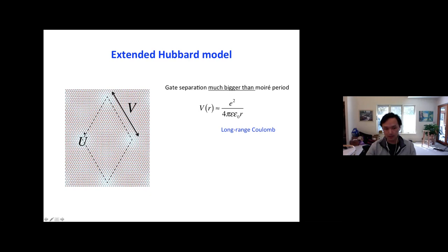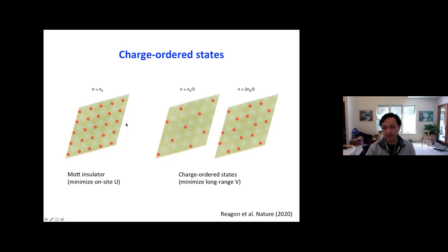So in addition to the local U, we should also consider the V between the moiré sites. The correct model to capture the physics is the extended Hubbard model, including not only the U but also the long range V. In fact, the effect of the nearest neighbor Coulomb repulsion was revealed by a paper this year by Feng Wang's group at Berkeley. In addition to the Mott state, they also observed two additional states at fractional fillings, one third and two thirds filling. These are interpreted as generalized Wigner crystal states or charge order states. This is basically an attempt of the electronic system to minimize the long-range Coulomb repulsion and form a charge order state.